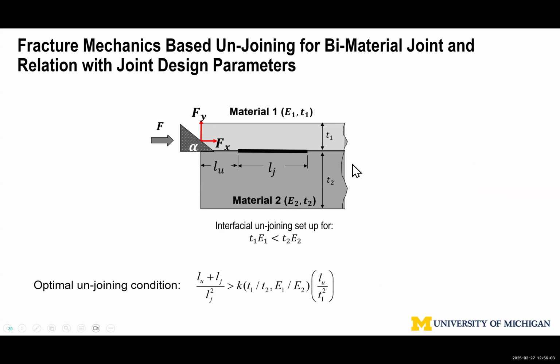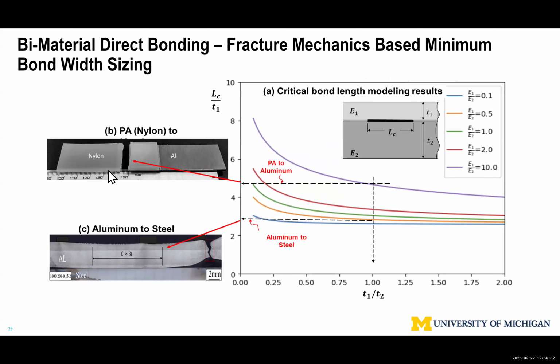I'm not sure if I answered your question. That was, I think what I was more asking, but that was really interesting. Let's say there's a hole in material two that a crack is originating from, and then it's propagating from material two to material one. What happens at that interface? That interface will be intact. So by design, you want to have that. If there's a failure, you want to have that failure because that gives you the best load capacity. I think that's corresponding to this case. Because you may have a bubble, some defects, and you want to make sure the maximum, minimum bonding length already accommodates those defects based on statistical analysis of the quality. Yeah, makes sense like that.